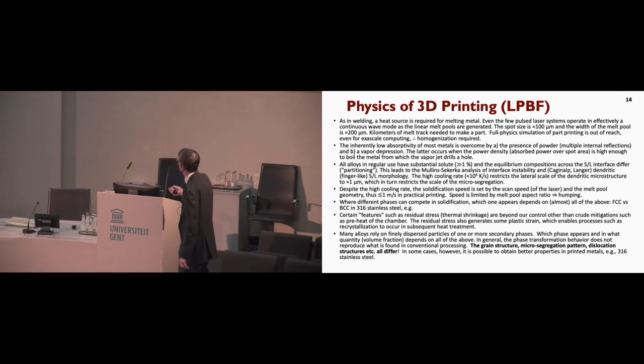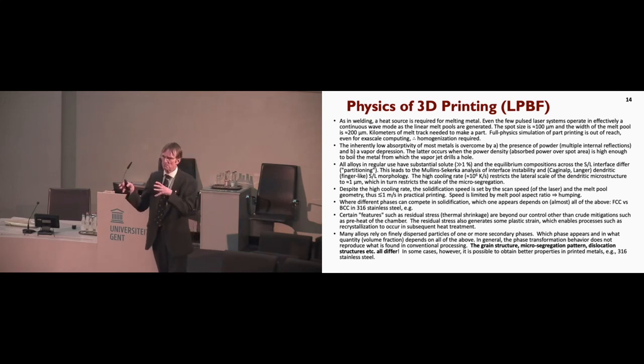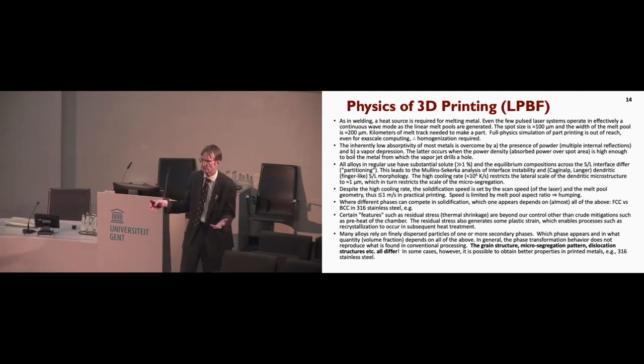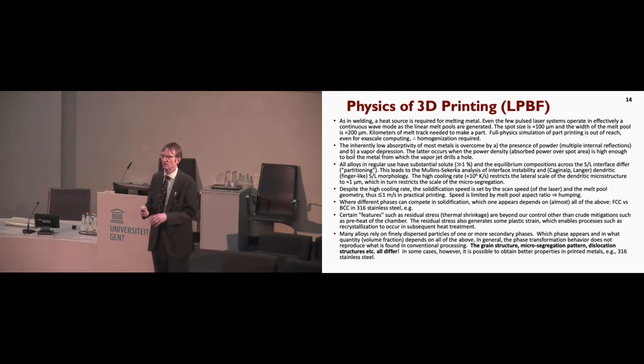But the bottom line, if you like, not to spend too long here, is that grain structures, microsegregation patterns, dislocation structures are all there, but they all differ very drastically from conventional material. And as many of you are well aware, you typically want to use the part, maybe with some heat treatment, but certainly not having to forge it or deform it in some way. So you're much more limited in terms of the total sequence of events.